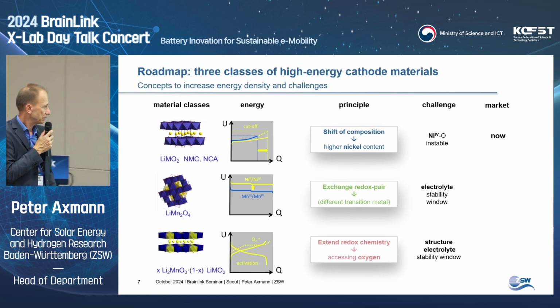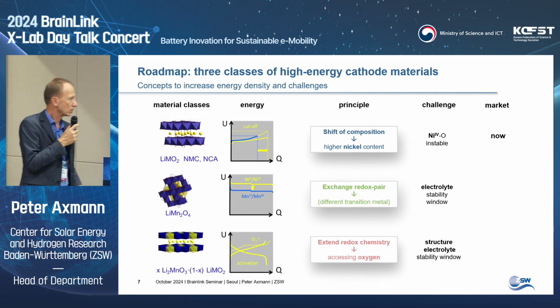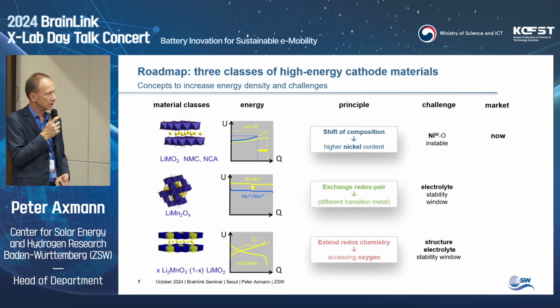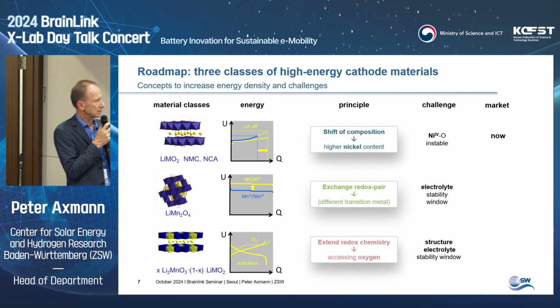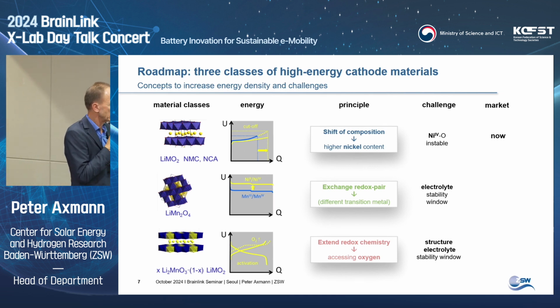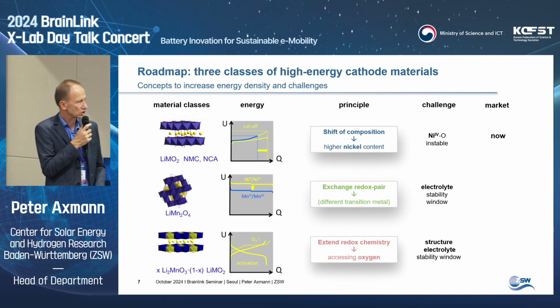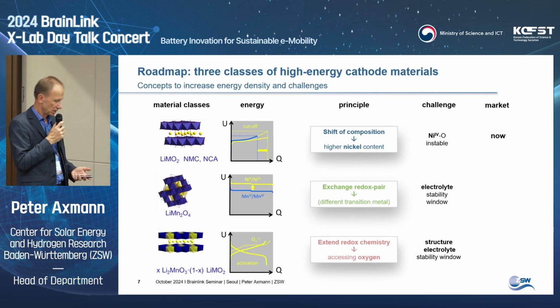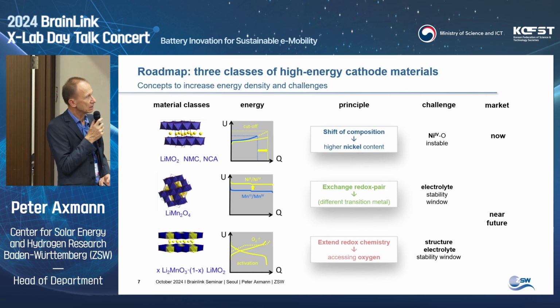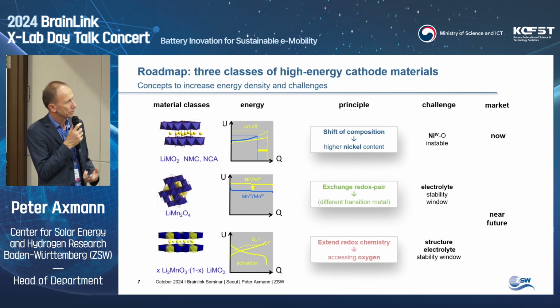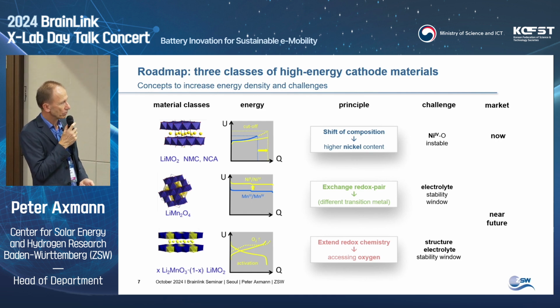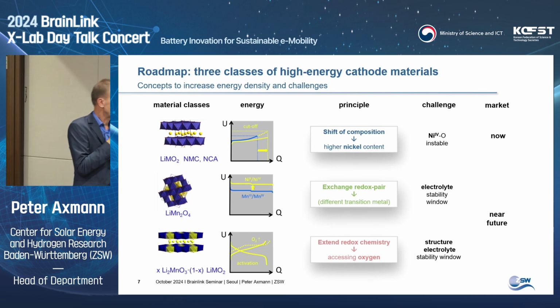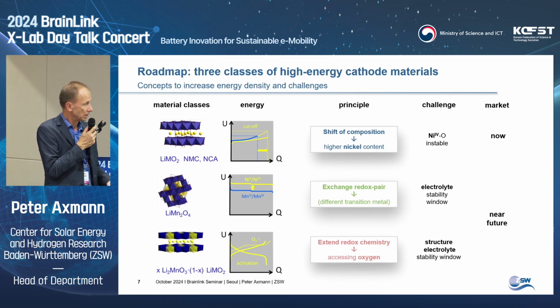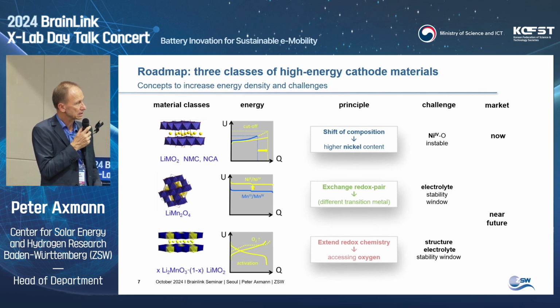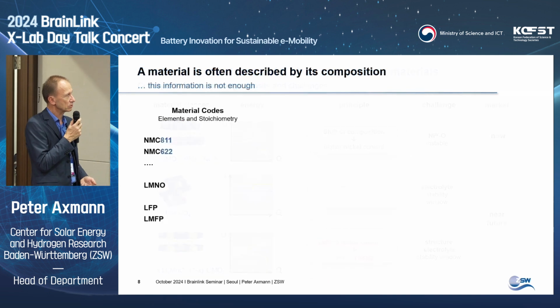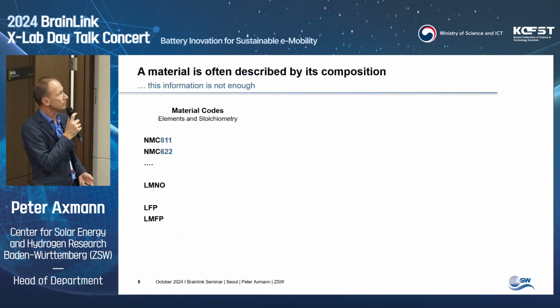And we go to a third part, and these are the lithium manganese rich layered oxides, and here you extend the redox chemistry going from the transition metals and access as well oxygen redox processes. And here as well structure and electrolyte stability window are the challenge which we have to face. The latter two materials are on the near future part of the roadmap, and they are really interesting because they have low nickel contents and they can be made without any cobalt, thus reducing the price drastically.